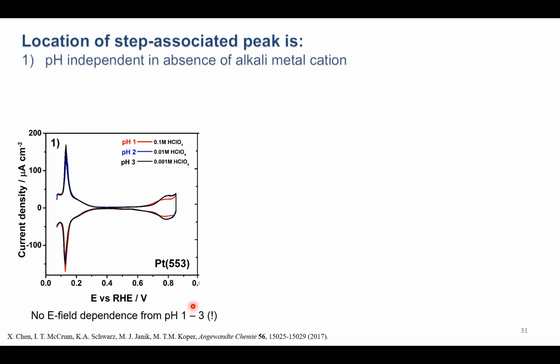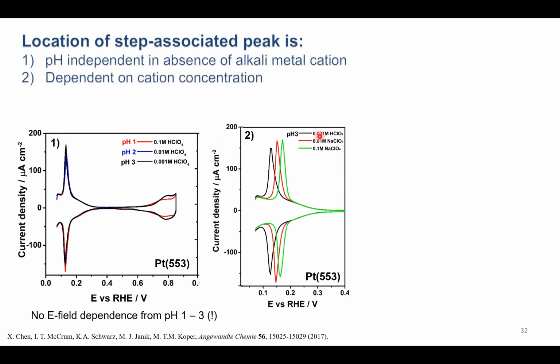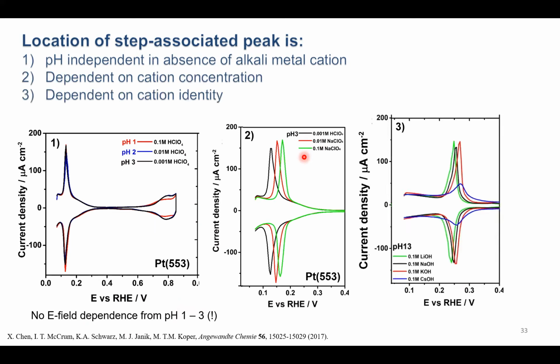Now, at pH 3, we can add the presence of an alkali metal cation and see what happens. We find once we add the cation at pH 3, the peak shifts. More importantly, if we increase the concentration of the cation at constant pH, we see the peak shifts more. This would support we have a higher coverage of the cation along the step, we shift the peak more. Lastly, at the highest pH, we see that the location of the peak depends on the cation identity. So we see a smaller shift with lithium and a higher shift with sodium, potassium, and cesium. So here we're looking at constant pH, and we see the identity of the cation has an effect.